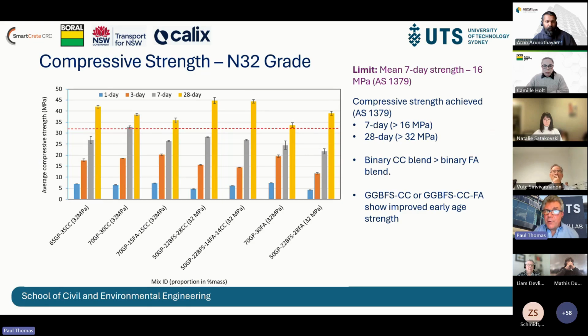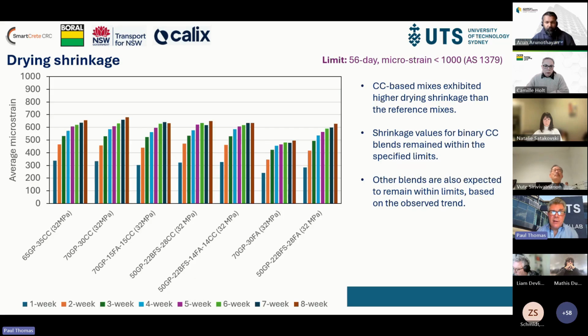Similarly for the blast furnace slag, very good workability retention. Now for some of the hardened properties, we made a 32 megapascal grade, and we easily reached it. In fact, the calcined clay blends produced higher strength than the fly ash blends, and also better early age strength than the fly ash blends, for both the blast furnace and binary fly ash substitution blends. So from a strength basis, we had really good results.